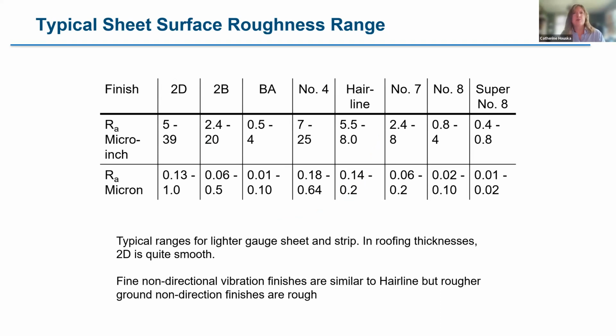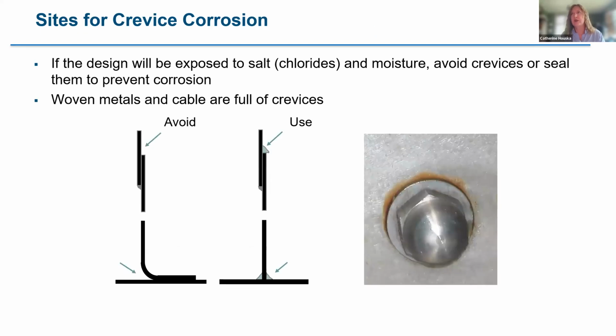In another Nickel Institute brochure, Timeless Stainless, I did a survey of finish suppliers in North America and Europe and included that in this table. You can see that a number 4 finish, which is very popular, can be very fine, or it can be rougher. So it could be on either side of the line that I just showed you. If you have an aesthetic application, or one where you really can't tolerate corrosion, it is important to not just say, I want a number 4 finish, but to also define the surface roughness, the maximum or range that you find acceptable. I usually suggest a range if you need to have aesthetic matching.